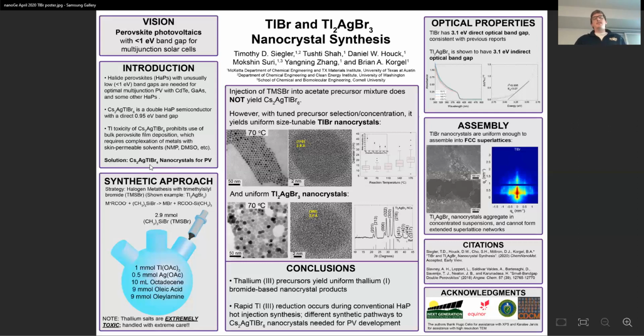try to, in a sanitary environment, synthesize cesium silver thallium bromide nanocrystals and then engage in post-synthetic deposition using established optoelectronic nanocrystal methods. To try to synthesize these nanocrystals as a first step in this process, we took a metathesis reaction developed for cesium silver bismuth bromide by the Gamelin group and attempted to adapt it for this system, taking metal acetate precursors and injecting the halogen donor trimethylsilyl bromide into our reaction mixture.